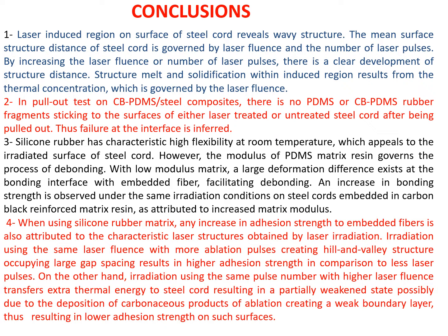Irradiation using the same laser fluence with more ablation pulses, creating hill and valley structures occupying large gap spacing, resulted in higher adhesion strength in comparison to fewer laser pulses.